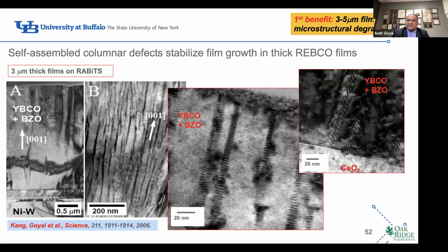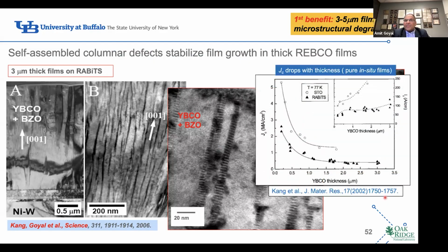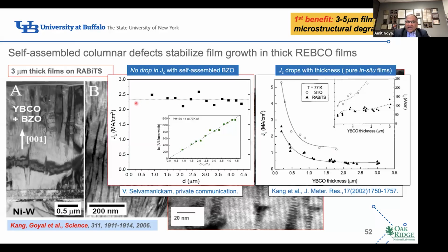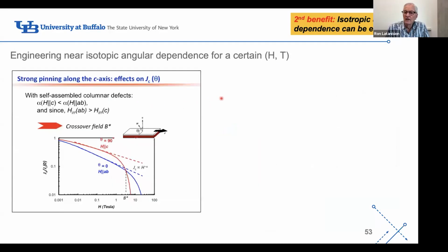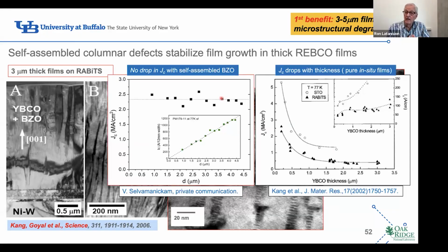I showed you this slide previously. If you didn't have this nanostructural modification, this is what one would get. Oops, 1 second. My slides. Okay. So if you plot the critical current density versus YBCO superconductor thickness without this nanostructural modification, you can see that as you grow the film thicker, the critical current density drops. When you have this modification, it doesn't drop. You can make them very thick. So it's providing stability, mechanical stability and keeping alignment.